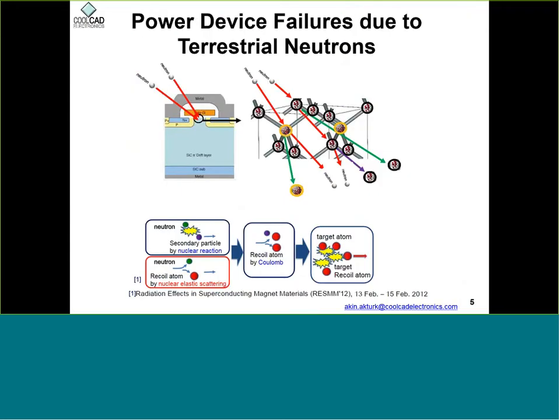So how do neutrons cause failure? Neutrons themselves do not interact with the material. They'll just go through the material without ionizing anything because they do not have charge. So the only way high energy neutrons cause damage is when they have a head-on collision with one of the lattice atoms. Since neutrons have high energies and appreciable mass, they can dislodge one of these lattice atoms. And a dislodged atom is very effective in depositing energy into the device. It will create electron hole pairs and that will create a short when the device is in off state. And that short can cause a catastrophic failure in the form of a burnout or a gate rupture, which I'll describe later.